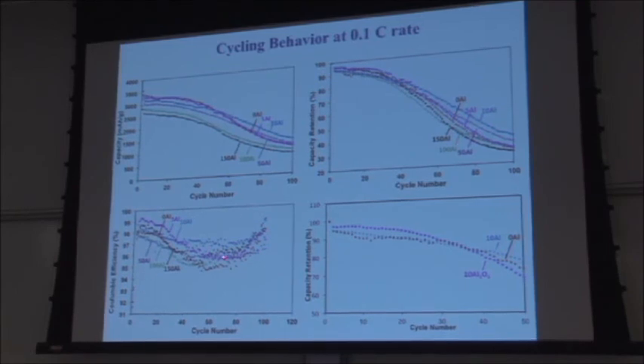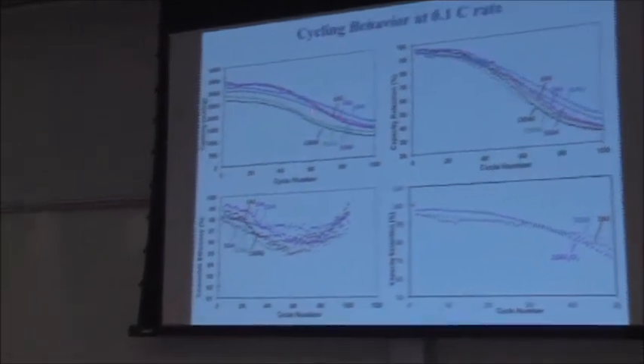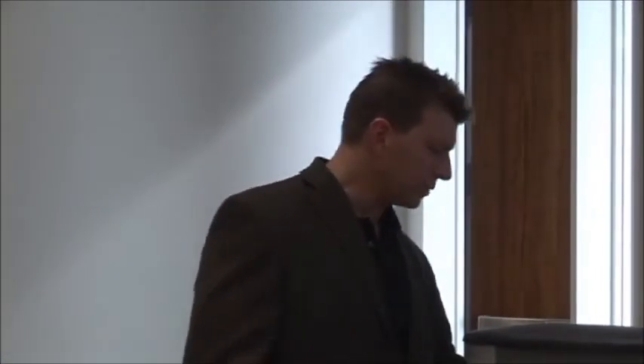And interestingly, with your Coulombic efficiency, once you have significant onset of failure of nanowires, the remaining nanowires presumably don't form as much SEI layer or something happens, but your Coulombic efficiency actually starts to increase once your capacity begins to degrade. So if you look at the capacity retention with ALD, initially it's a little bit better, but if you run out to 50 cycles, it's actually worse than with just pure nanowires without the aluminum coating. So the 5 and the 50 nanometer aluminum really seem to improve things, though not tremendously.